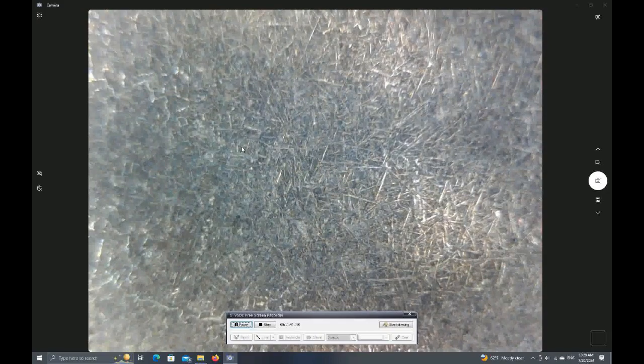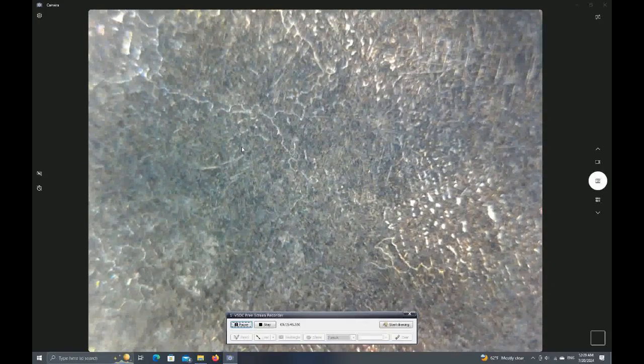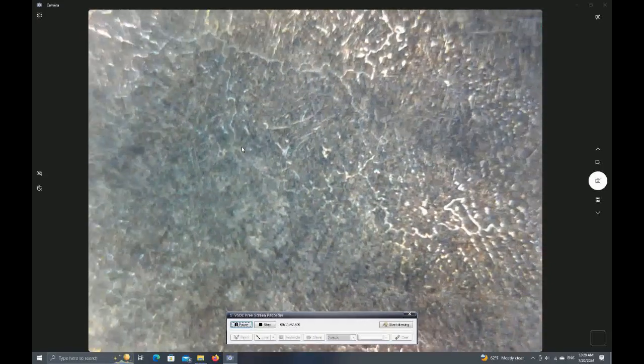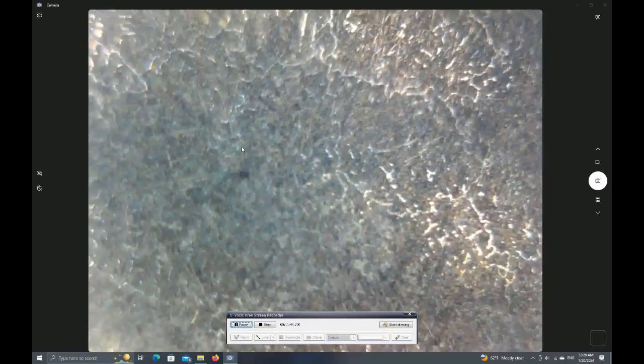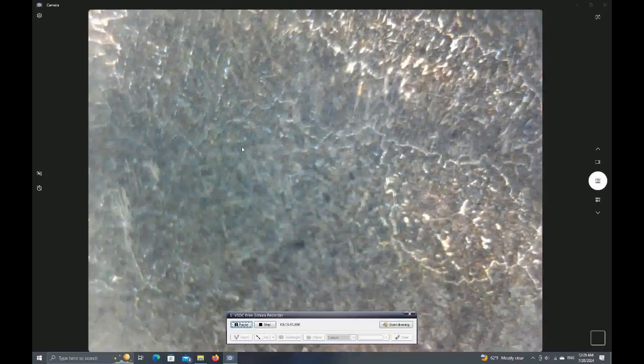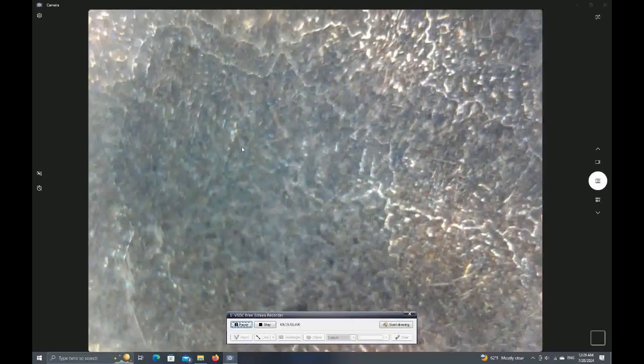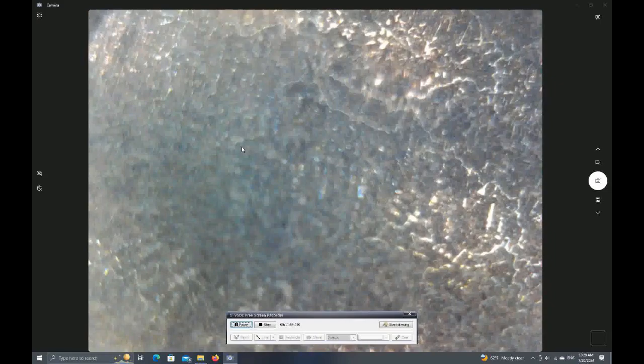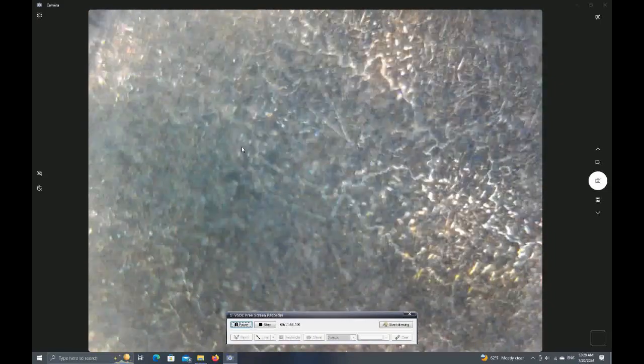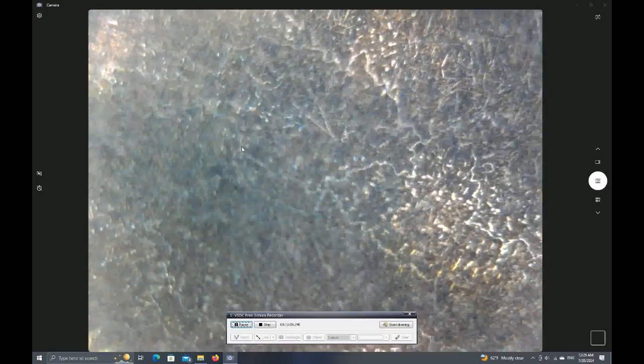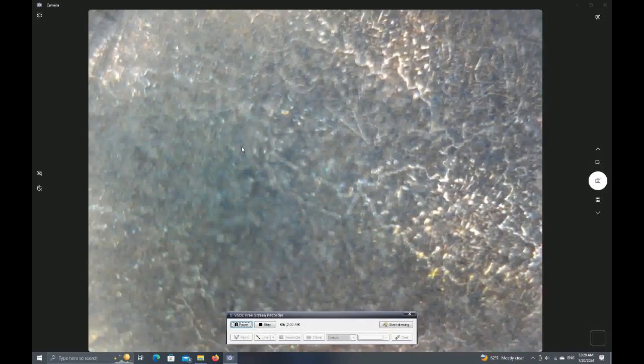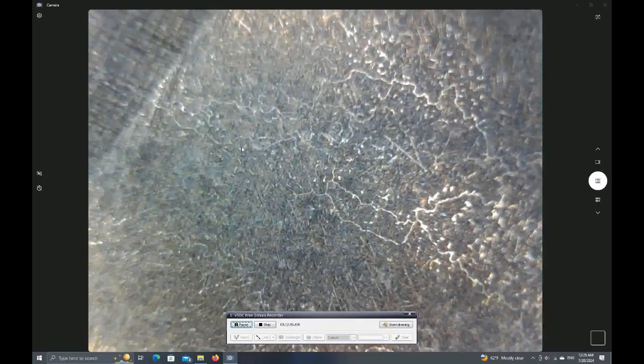So I really don't think that's a feature attributed to my lack of polishing. And again, we're seeing more of a close-up view of these borders, these grain boundaries. It's a little bit messed up because of the way the light is introduced in this little microscope, it's got a built-in light. You don't see the reflection of carbide formation on the grain boundaries in the center of your field of view. You see it off to the periphery. Let's fix our zoom a little bit better there.